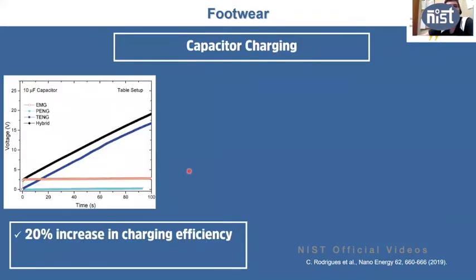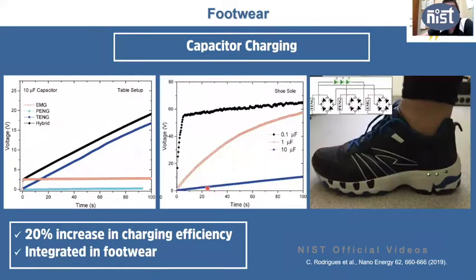If you now charge a capacitor with these structures, this is why we should consider all of this hybridization. If you have only the piezoelectric, you don't charge the capacitor at all. If you have the electromagnetic, you charge it very fast, but then it saturates because the output voltage that you get from the electromagnetic generator is very small. If you have the triboelectric, you have basically a linear increase of the voltage at the capacitor. But if you use the hybrid generator that we have made, you have a fast increase coming from the electromagnetic generator at the beginning, and then you have the steady increase that comes out of the triboelectric generator at a later stage. And this gives you a 20% increase in the charging efficiency.